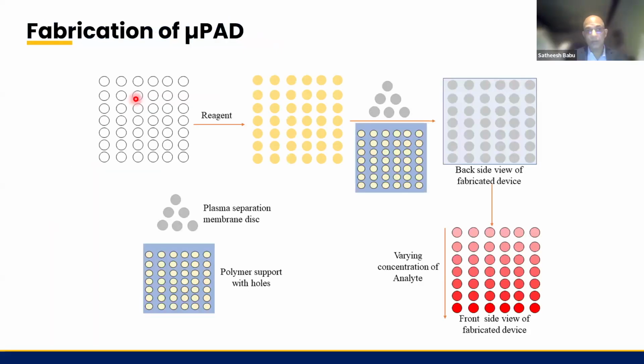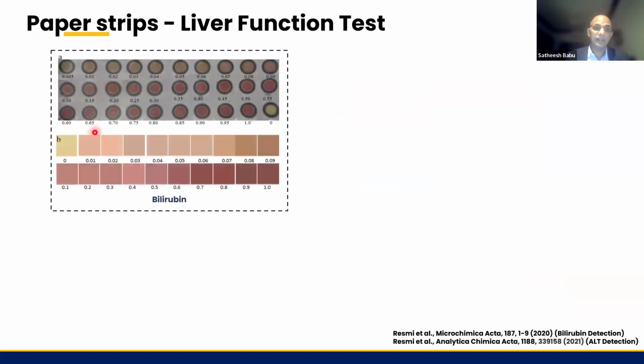And what we have followed was we took a Whatman chromatography paper patterned using wax printing. Then we introduced the reagent corresponding to that particular analyte. Then we used the plasma separation membrane. And also we supported with a polymer support because it's just a Whatman chromatography paper. Then we introduced the sample, and with an increase in concentration, we find an increase in color intensity. As samples, you can see here the bilirubin we tested from very low concentration to very high concentration here. And we find an increase in color like this.